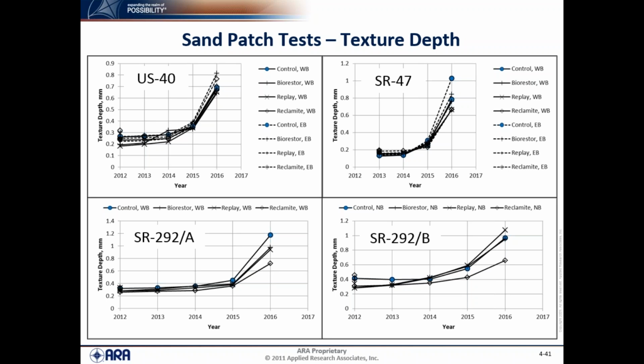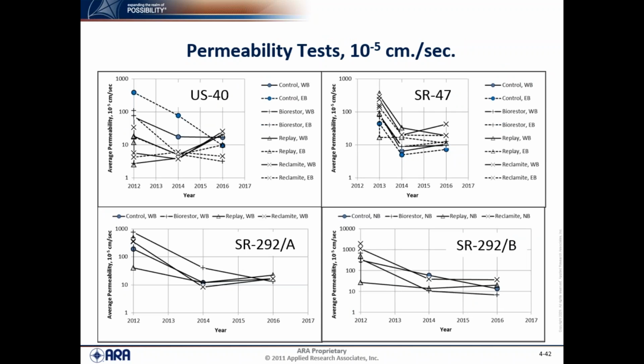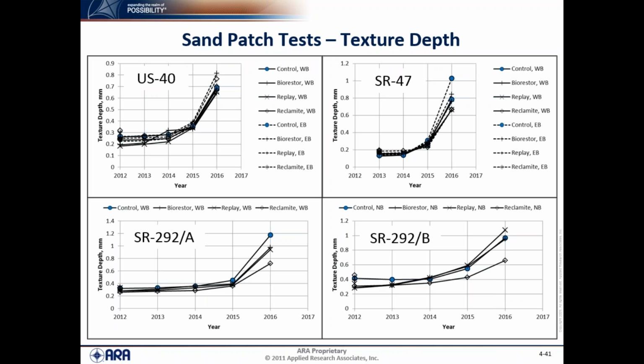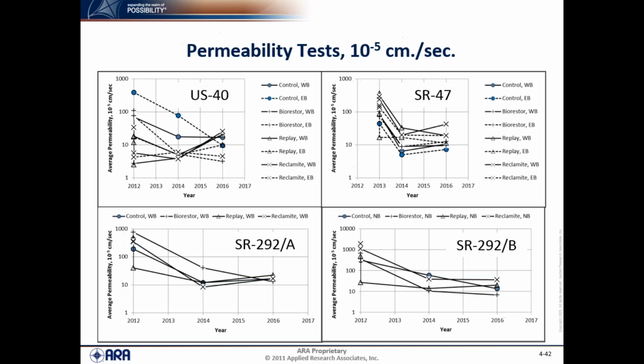So they're all still relatively low, even after about 4 years of time. This just shows the field permeability test. You can see from where the sand patch texture depth kind of crunched, about the same, especially when we're looking at the early end. For the field permeability test, that wasn't the case. We saw a lot of difference between test sections, a lot of difference over time.